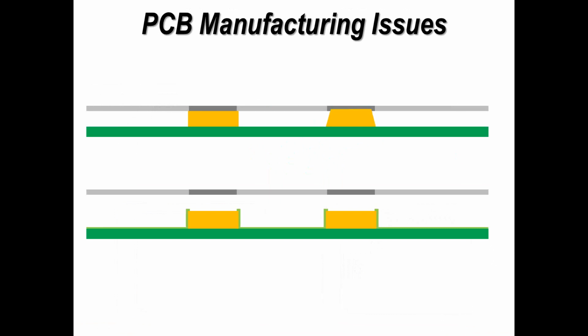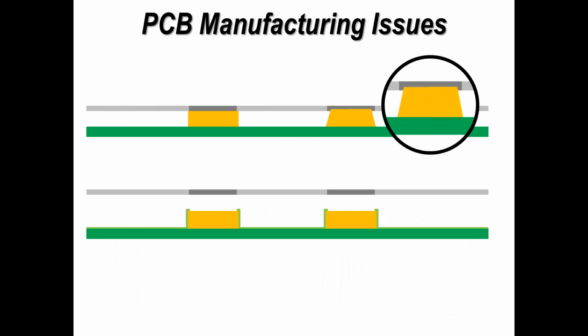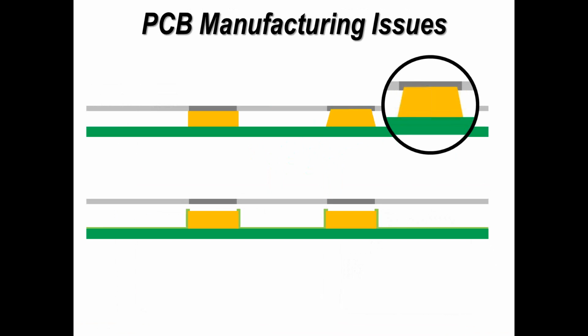So when we actually go through to printing of 0201, 01005 and smaller, the solder paste deposit is not actually in contact with the surface of the pad. It's in contact with the top of the pad, which may be a smaller area than on another pad. And if we look at a close-up of this, we can actually see the pad intruding into the stencil design. And it's not uncommon for design engineers, process engineers like myself, to actually create a stencil which is slightly larger than the pad on the printed circuit board because it makes printing easier. But in this situation, it can actually contribute to problems.